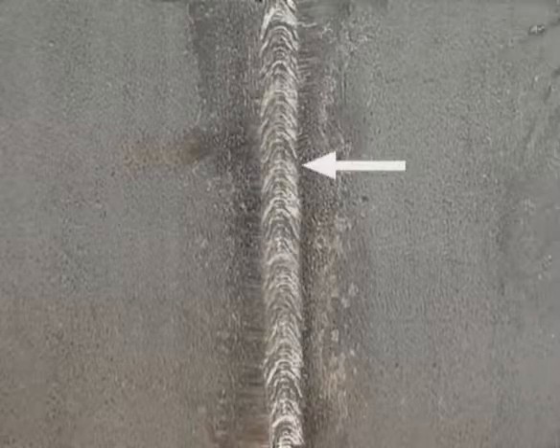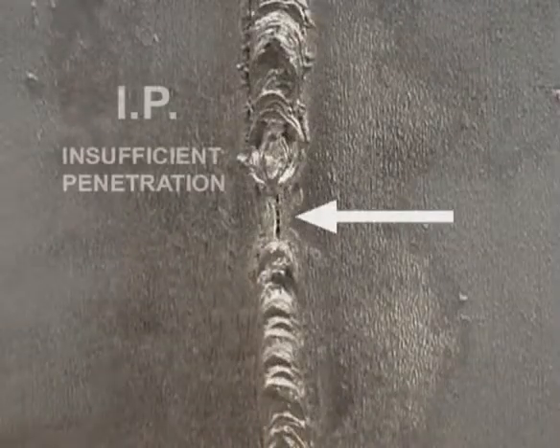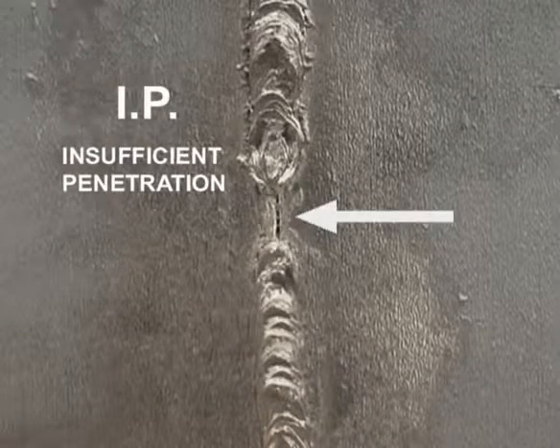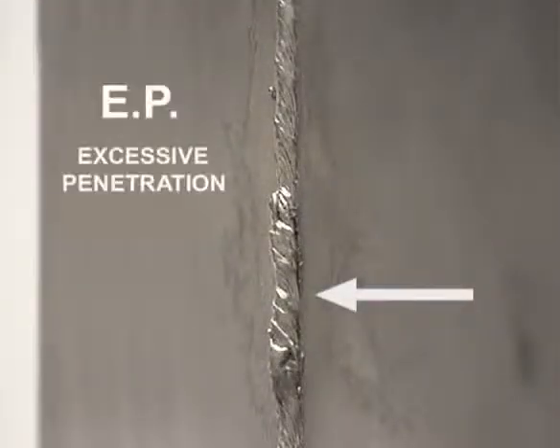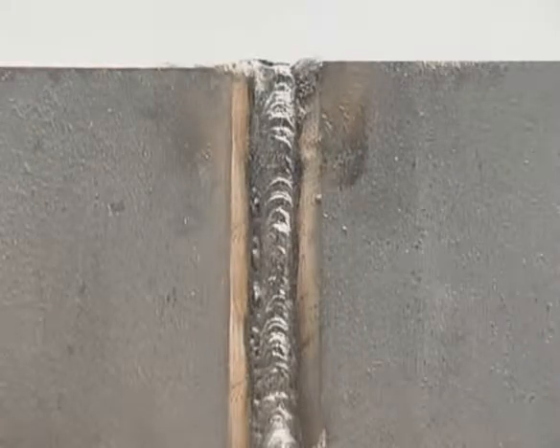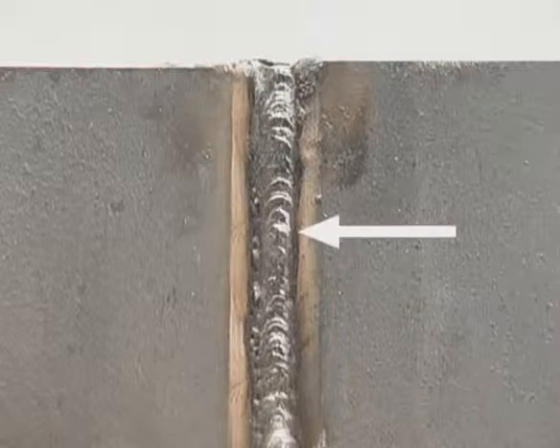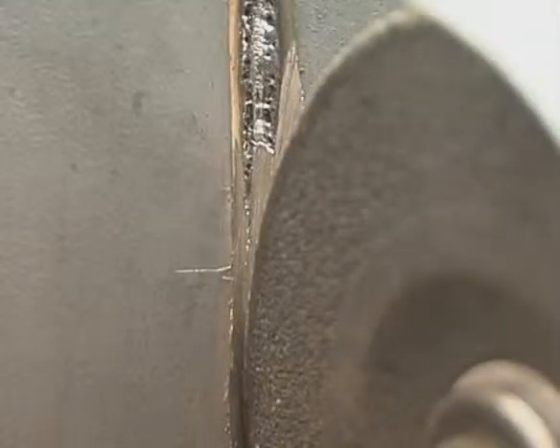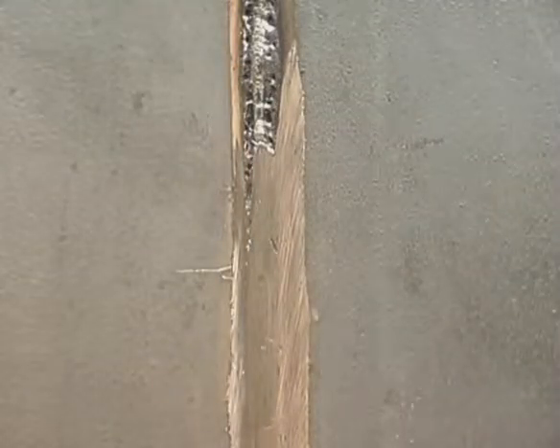The backside bead should be above flush, with the entire bottom edges of the bevels melted and fused. Any missed spots are called insufficient penetration. If the travel speed was too slow, the bead stacks up on the backside, causing excessive penetration. On the front side, because the rod was jammed right down against the metal, the bead will crown and undercut along both sides. Grind this out to avoid trapping slag.